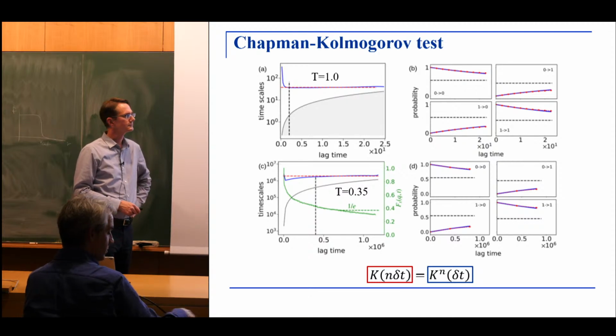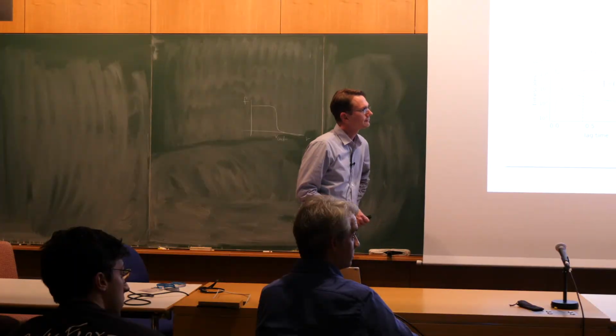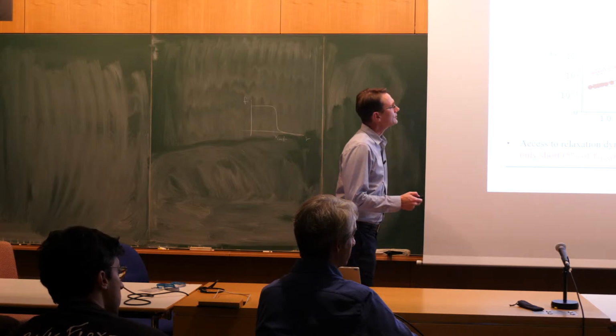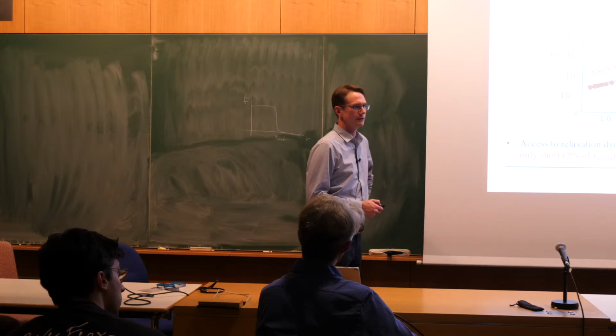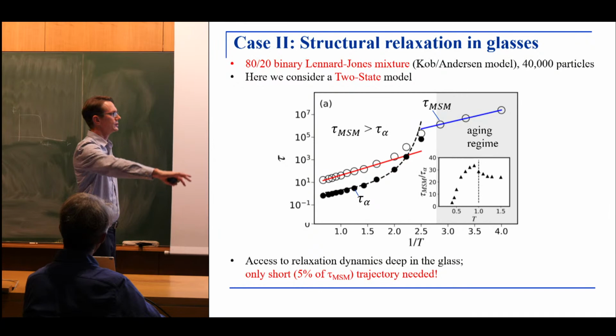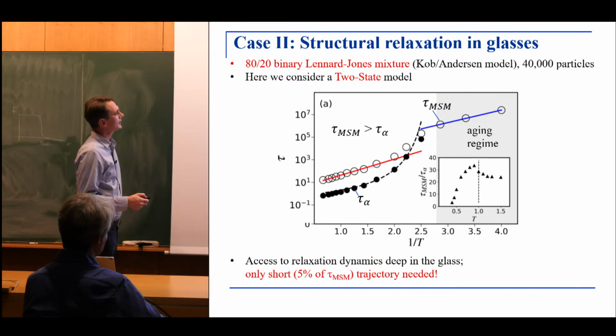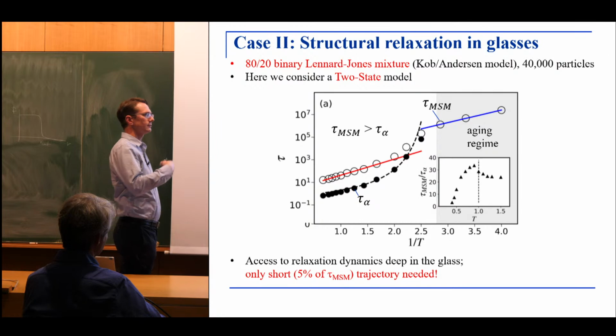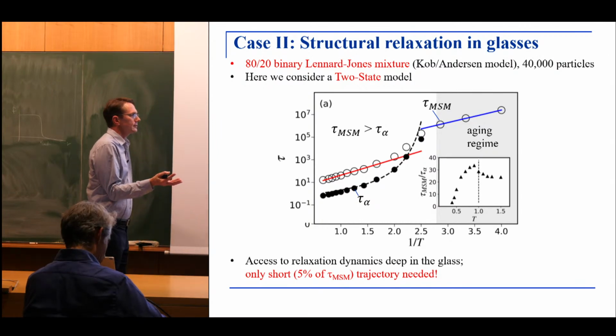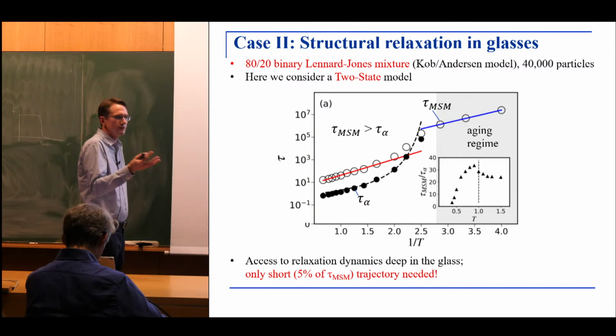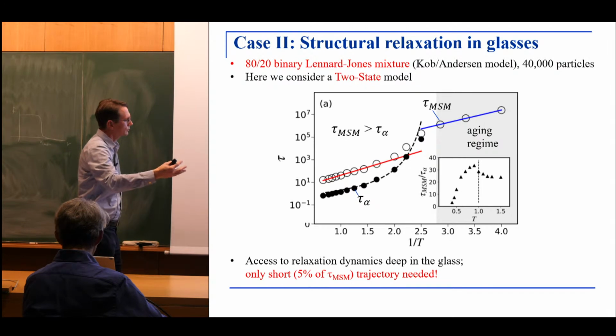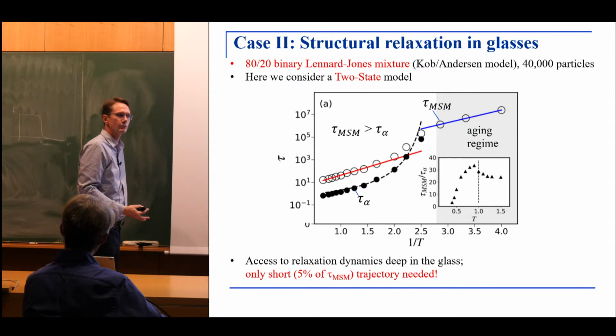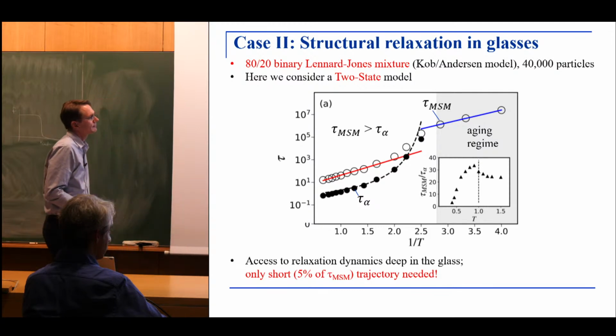So do we have more questions for Joerg? You didn't say anything about the aging regime, where instead the relaxation time seems to be quite different from the extrapolation. So what do you have to say about this one? So in the aging, here the glass is no longer in equilibrium because we're not using a swap or anything. It's just a brute force MD simulation. So if one were to let this glass age and repeat this measurement, one would find a different time scale. So the Markov state model time scale will become history dependent, just as any other observation time scale that you would measure from your self-intermediate scattering function decay, right? And this aging will, of course, continue until the glass would, if it could, be observed all the way out to equilibrium.